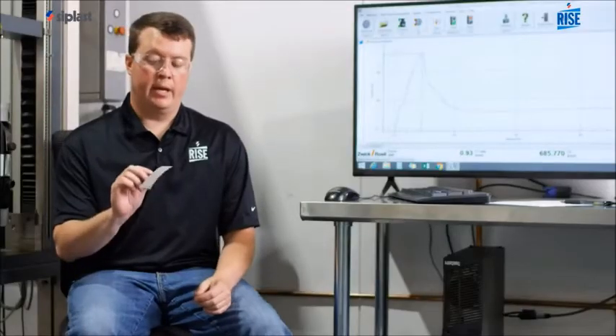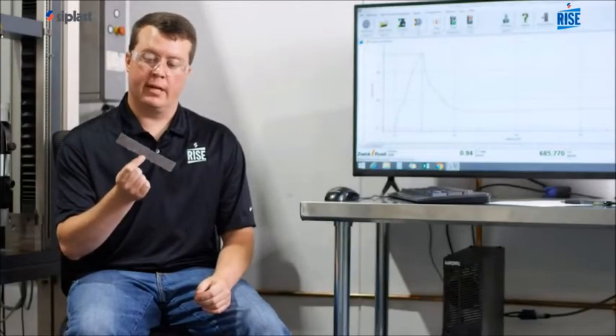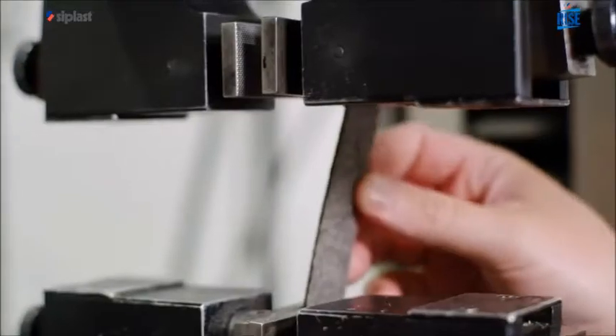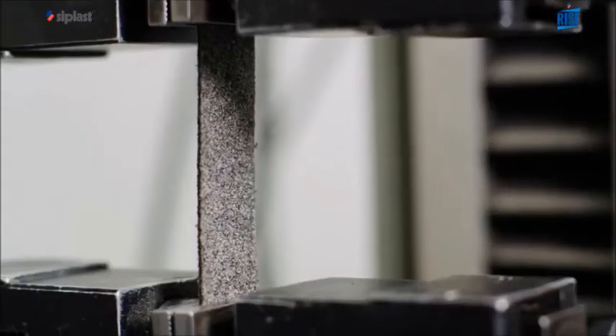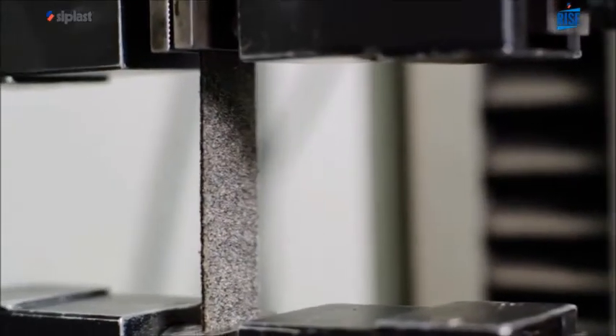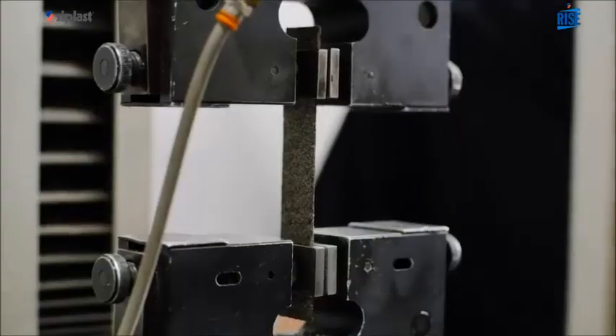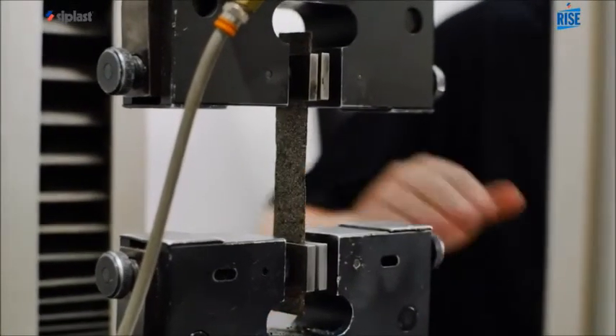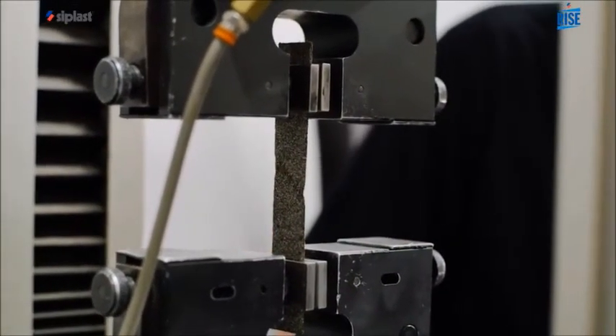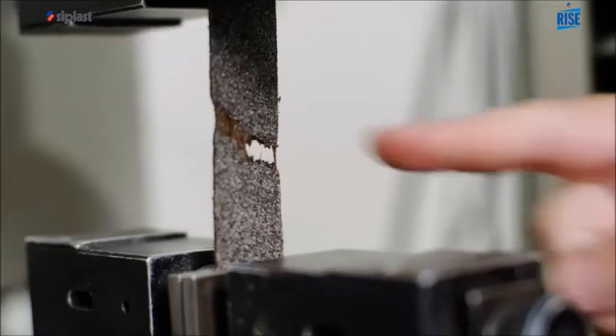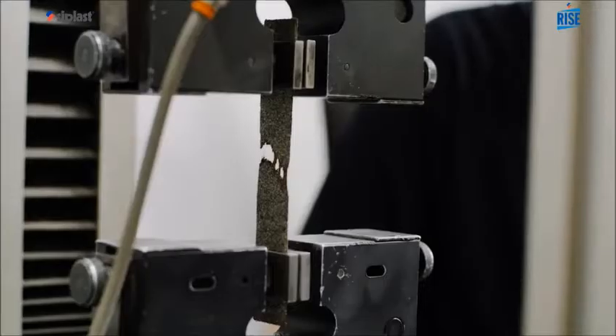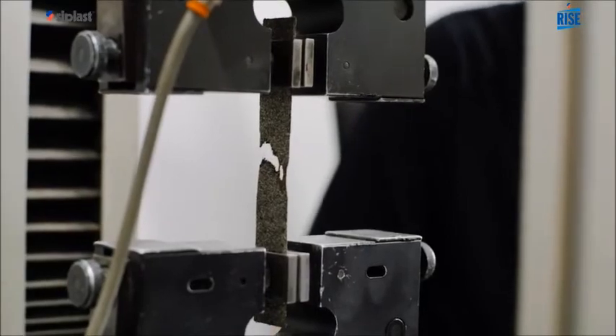So here we have a competitor base sheet product. This has a fiberglass reinforcement in it. With this product, it's got a higher filler content, lower polymer content. If you watch here, as we start to apply the load, we're going to see that reinforcement break. We see a little bit of elongation there, but as you can see quickly, we're starting to see that blend tear. Now we're at about the ultimate elongation point.